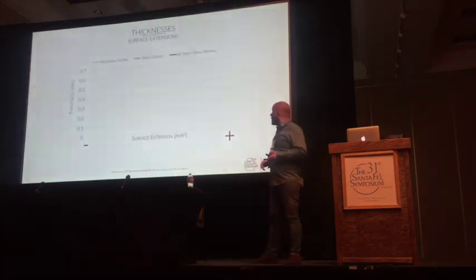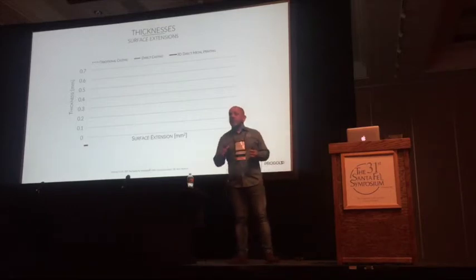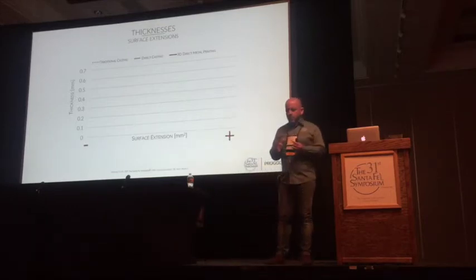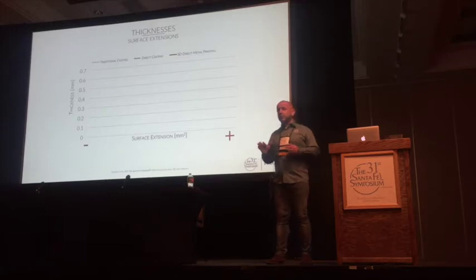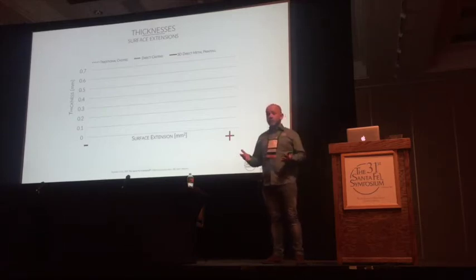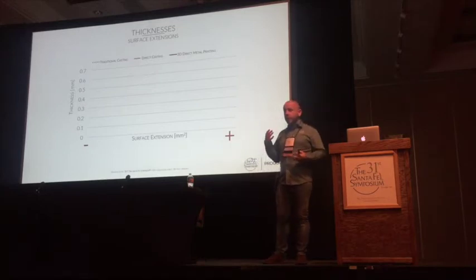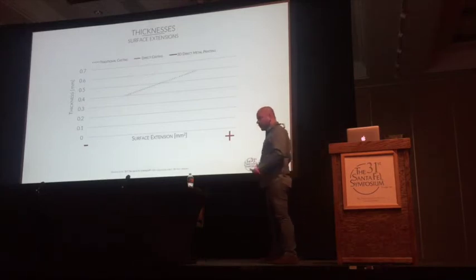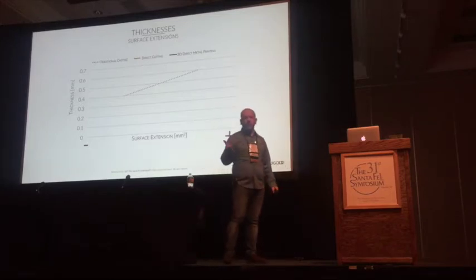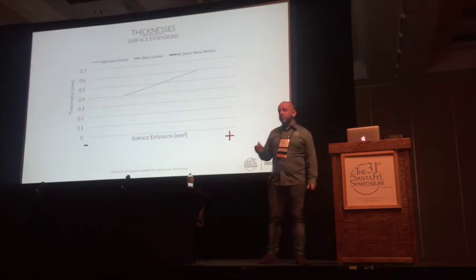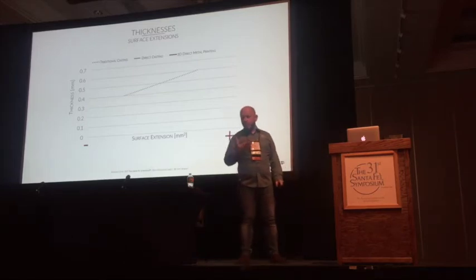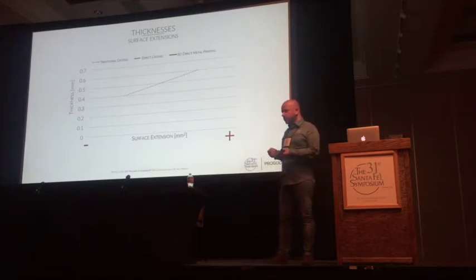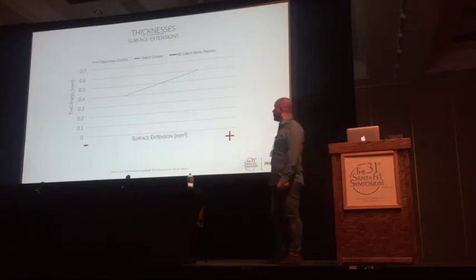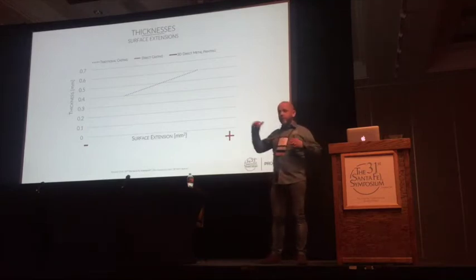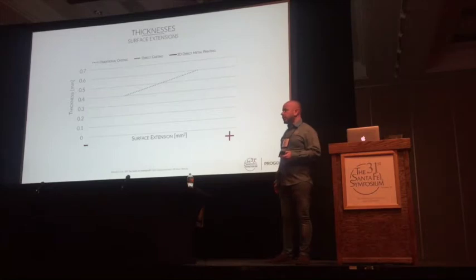Another important issue when we talk about thickness is the surface extension. It is easy to reproduce something thin but very small, and much more difficult to produce a very wide and large surface, like a hollow ring or hollow earring. So, in general, when we talk about casting, a thickness of 0.4 millimeter is common. Going down is quite difficult, not because of a casting problem, but because of wax, because it's difficult to make waxes thinner than 0.4. And then if the surface is getting bigger, you have to consider a much thicker cross-section.